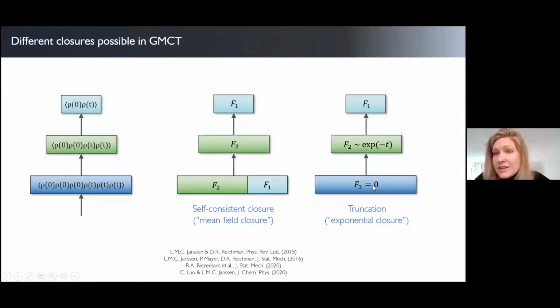There's also not necessarily physically any good reason to do that, but that's an alternative approximation you can use. In that case, it means that in this example, if we set the 6-point correlations to 0, the 4-point correlation functions here then decay without memory because we set the memory to 0. So these will just show simple exponential decay. And that will then be the memory input for the 2-point correlation function here. And so we refer to this as an exponential closure.